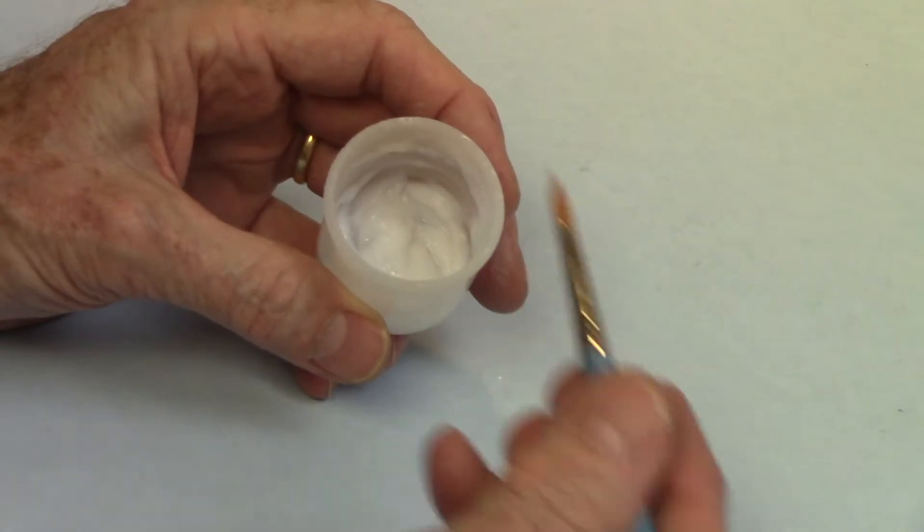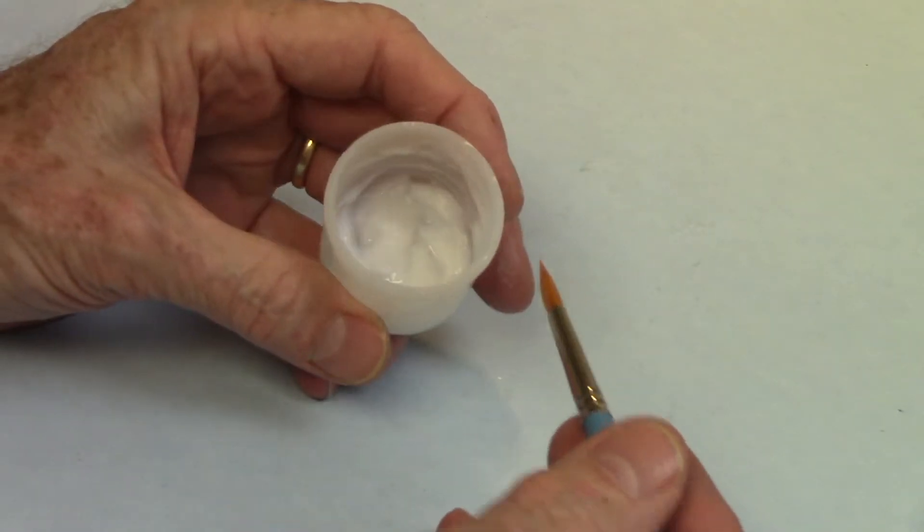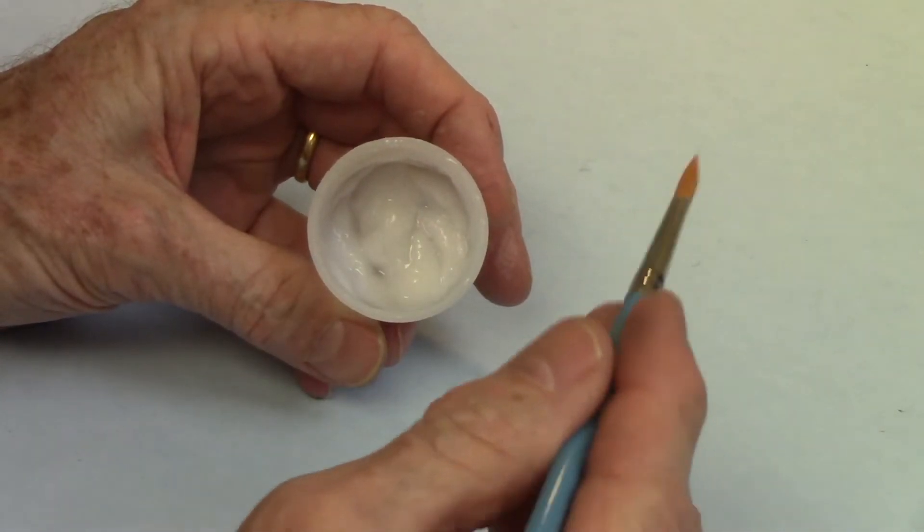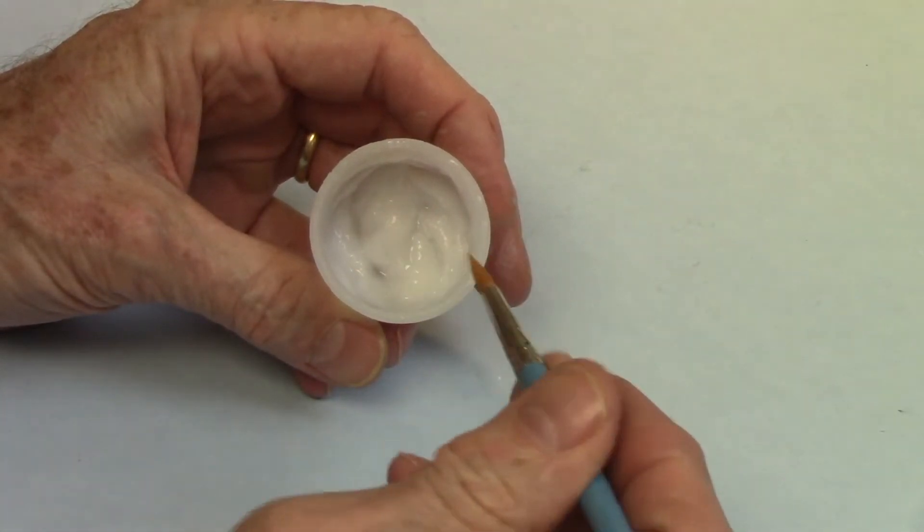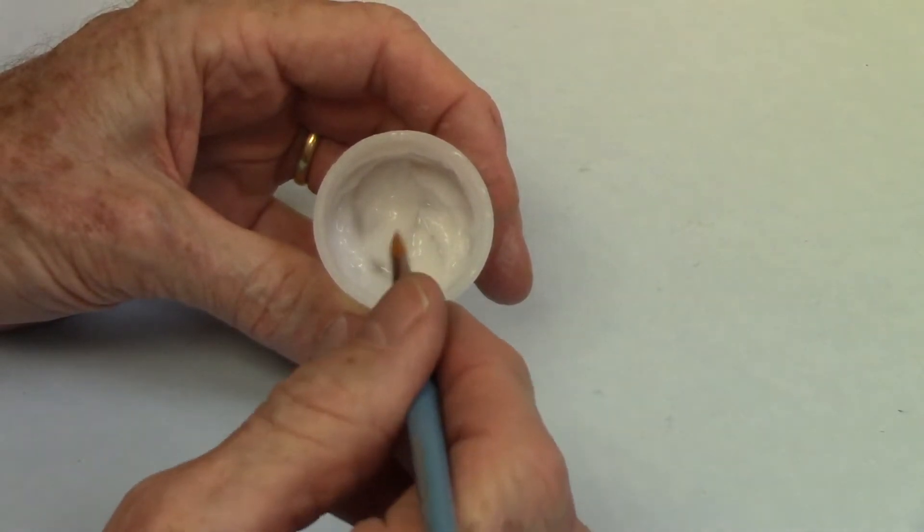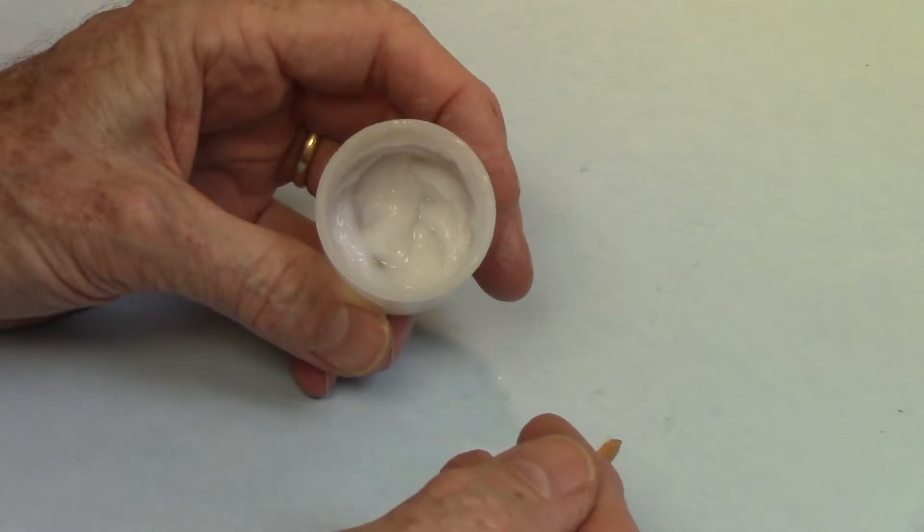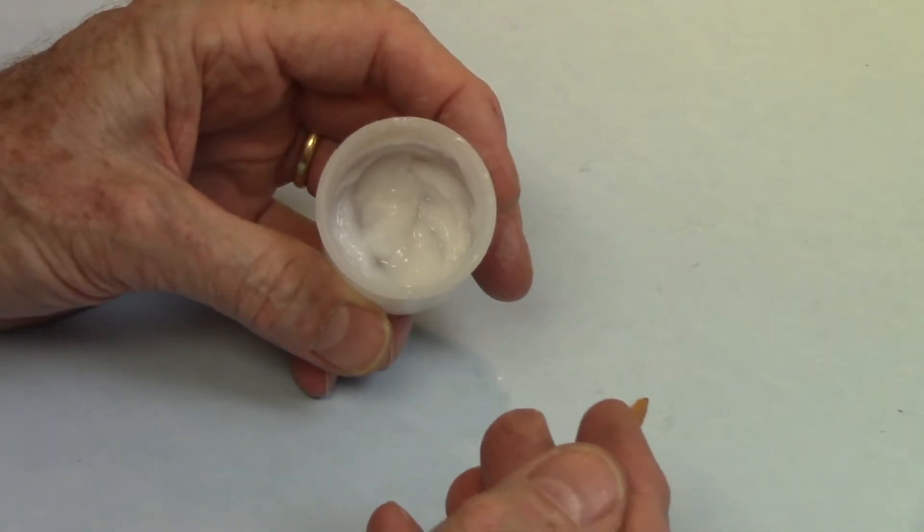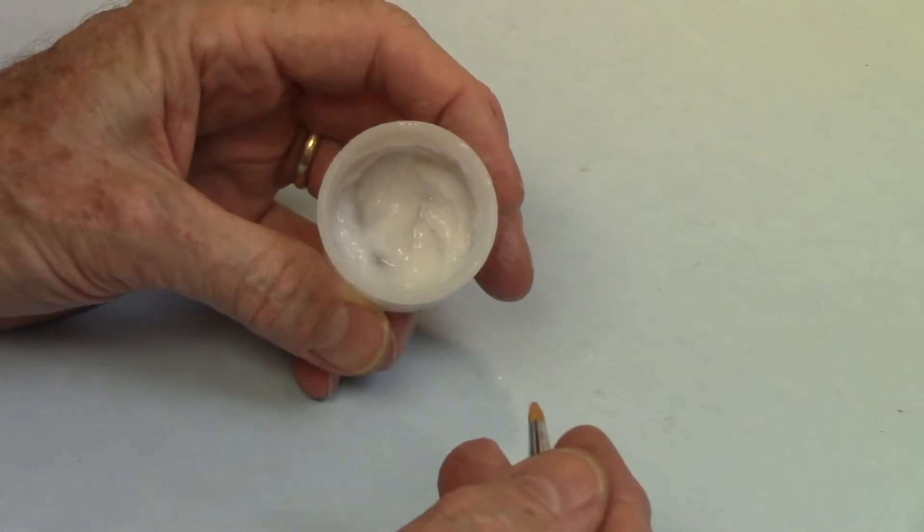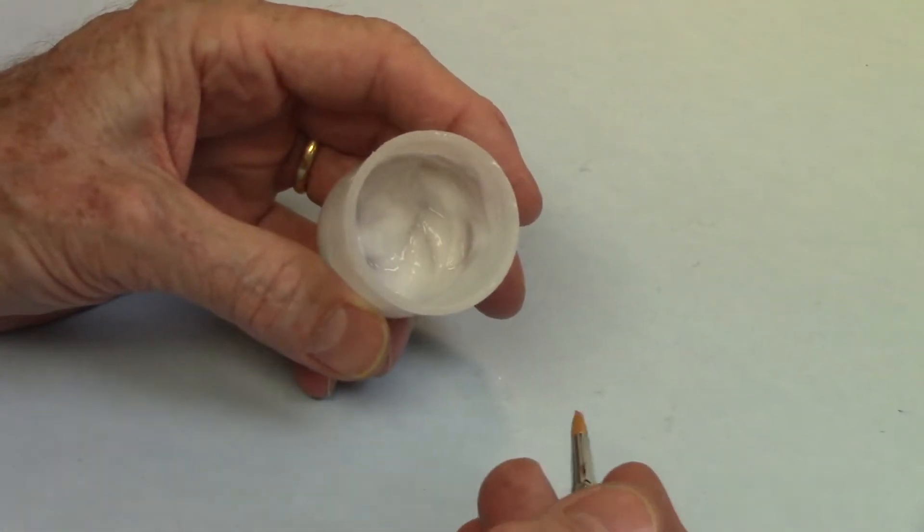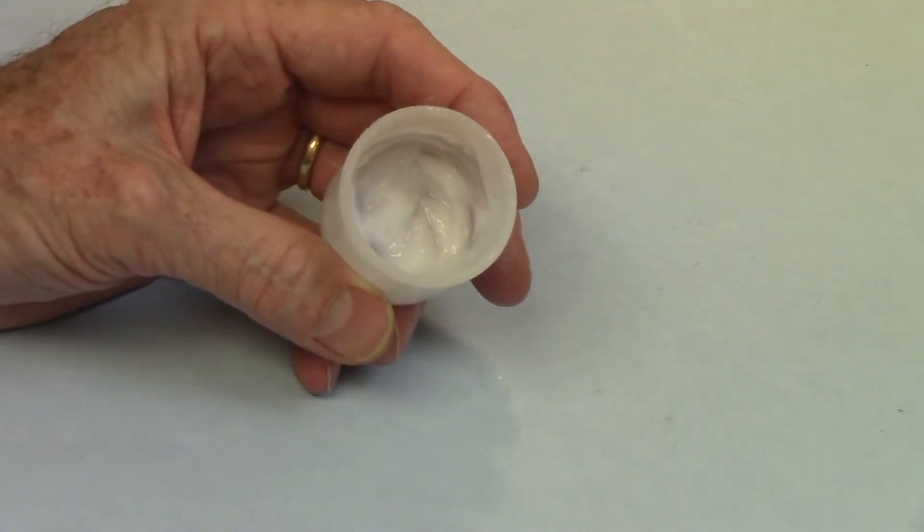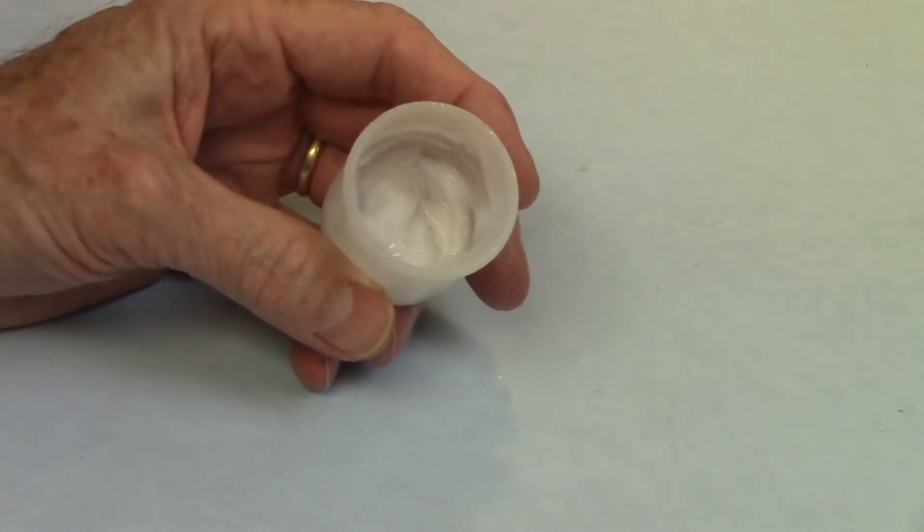So they said in college chemistry, you cannot contaminate the reagent bottle. So let's take that to our practical application in soldering. We can take it out. But if you have excess, like this, don't wipe it off because you can take contaminants from out here and put them in here. And contaminants have their impurities and they can combust and vaporize because they have lower temperatures usually and that can cause bubbles. That's one of the causes of bubbles. Now that's a refrain you're probably going to hear throughout this video. Do not contaminate the reagent bottle.